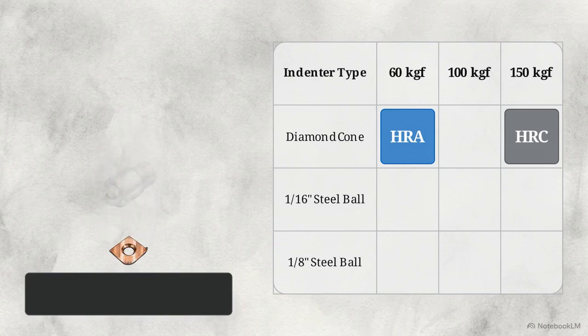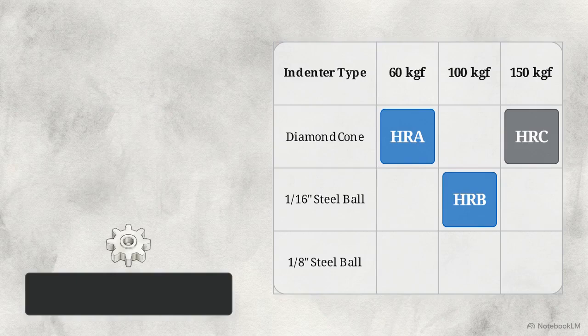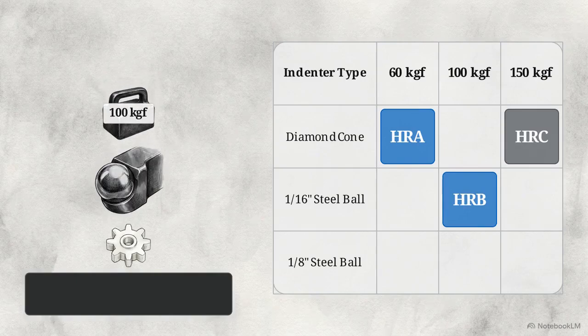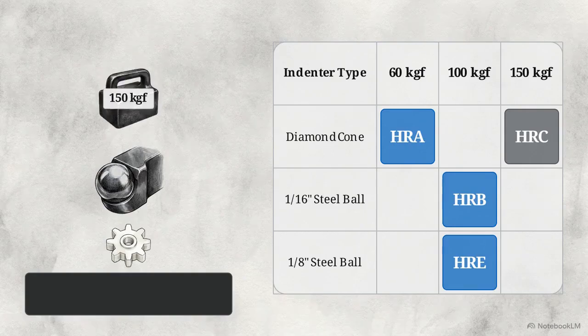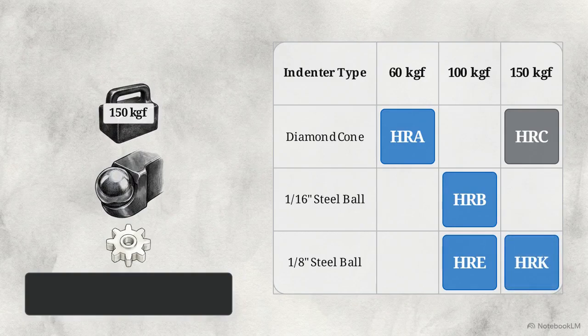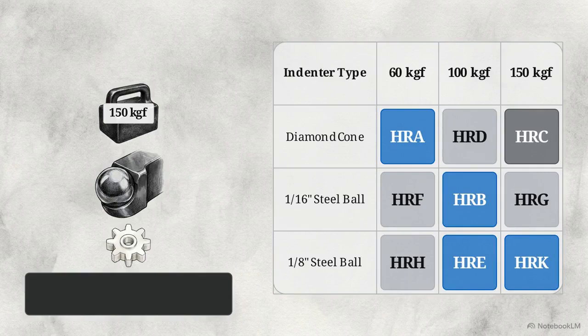If we test soft aluminum sheet metal, the sharp diamond point would pierce right through the specimen, regardless of load. Swapping the diamond for a blunt 1/16-inch steel ball and applying a 100-kilogram load establishes HRB, the solution for yielding soft metals. The remaining permutations cover the extreme edges of material vulnerability. Combining the 1/8-inch ball with 100 kilograms gives us HRE for cast iron, while pushing the load up to 150 kilograms creates HRK, tailored for plastics.